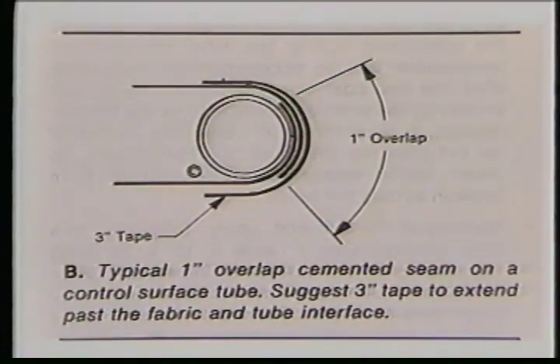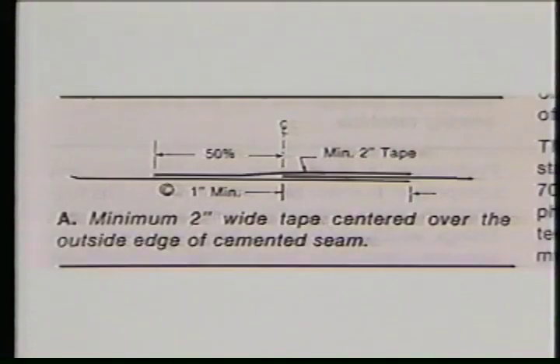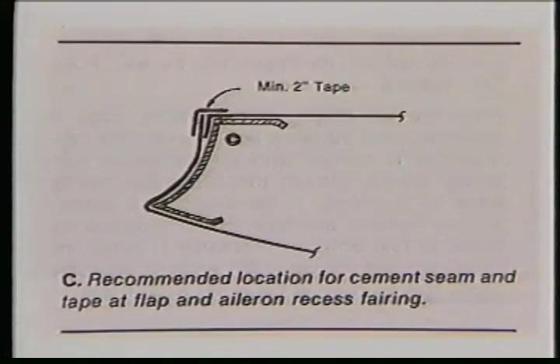A 1-inch overlap fabric-to-fabric polytack cement seam is stronger in shear loading than our strongest fabric, and in tension tests, the fabric always fails first. In peel tests reported in the manual, polytack develops over twice the bond as any nitrocellulose fabric cement. The polytack cement seam approval allows a 2-inch overlap at the wing leading edge and 1-inch overlap at all other areas of the airframe, each covered with a minimum 2-inch finishing tape regardless of the aircraft red line. All cement seams are made over a structure, not in open panel areas.